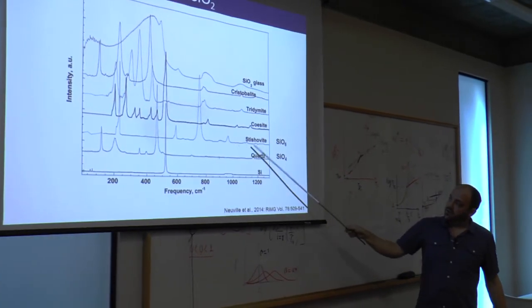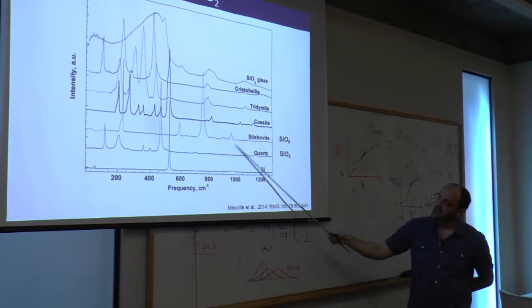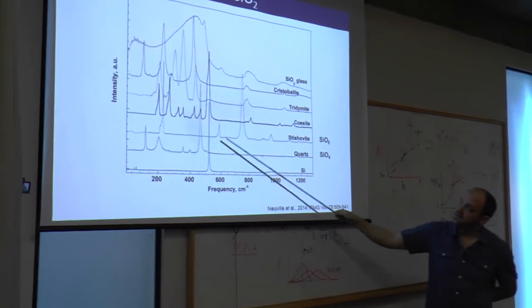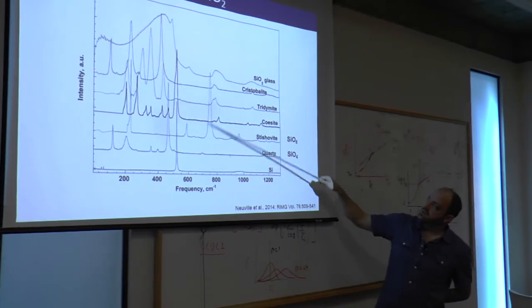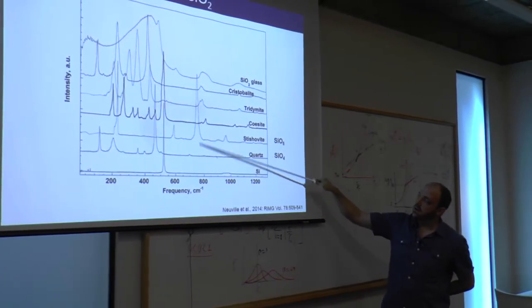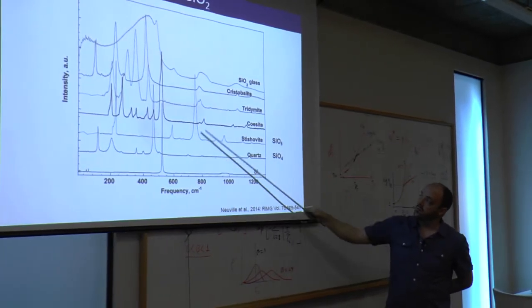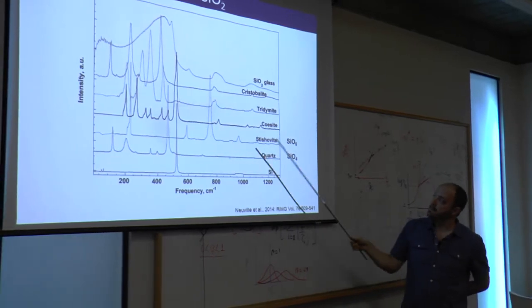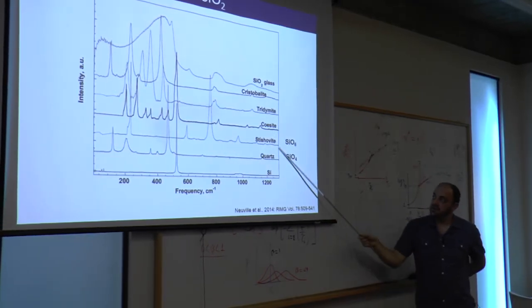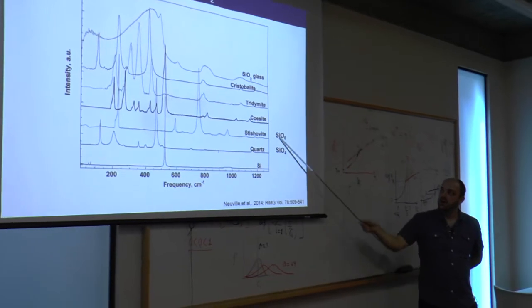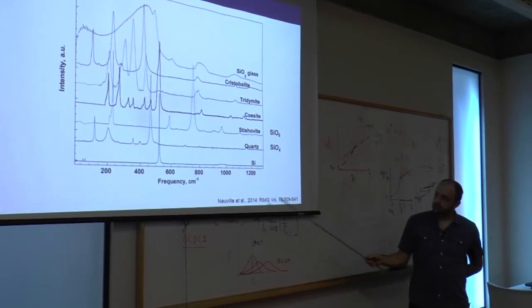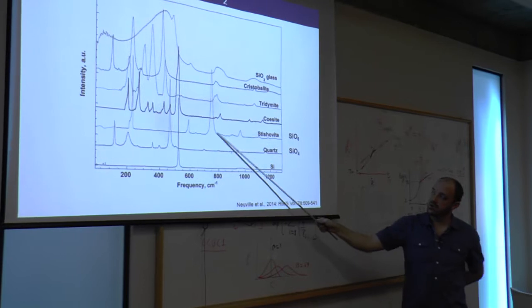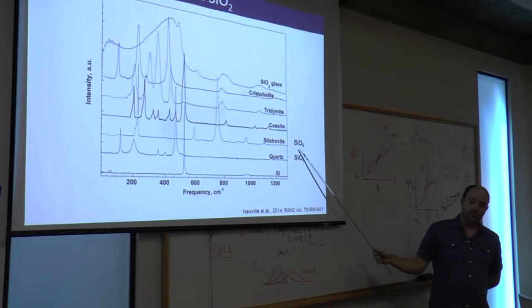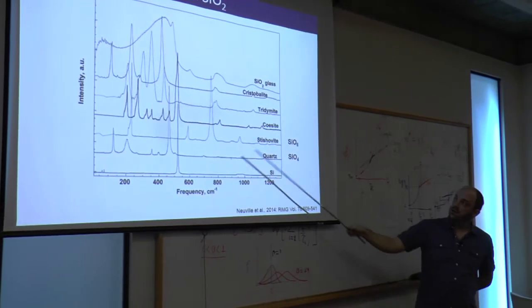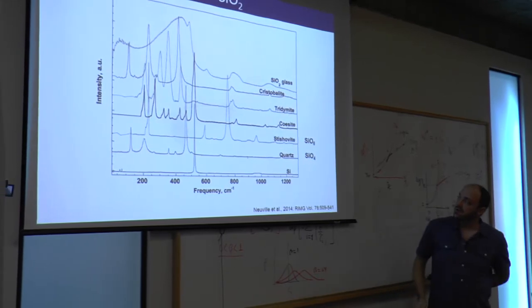The only other thing I want to point out before leaving here is that stishovite only has a couple of peaks here that are strong, but its most intense feature is at quite a higher wave number than these other minerals. It's because stishovite is the high-pressure form, which forms silica octahedra. So typically when we go to high pressure and we start to interpret 6-fold silicon, we get a band up in this part of the spectrum.